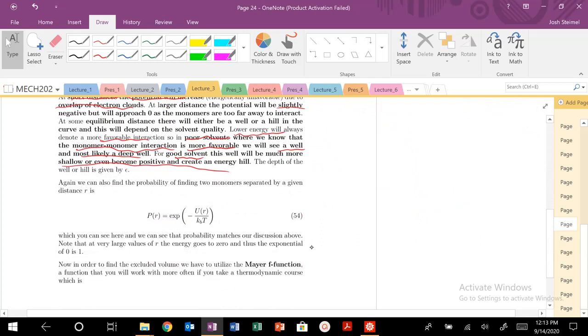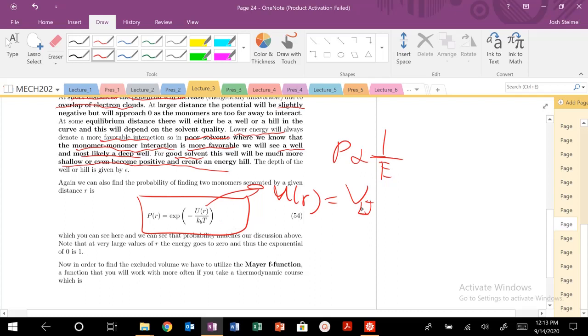One way we could find the probability from our energy landscape U(R) — which is equivalent to our Lennard-Jones potential — is: we said that if we take an energy landscape and take the exponential, we could find the probability. So we take the exponential of our energy landscape to find the probability of finding two monomers close to one another. At very large values of R, the energy goes to zero, and the exponential of zero equals one.